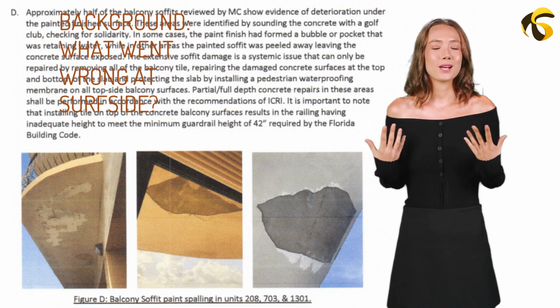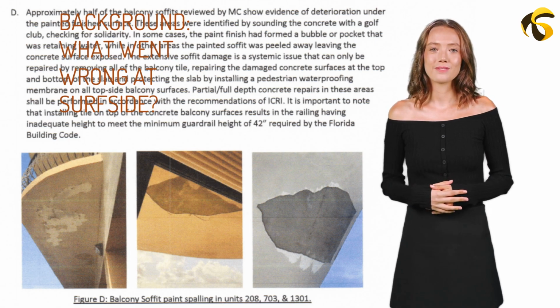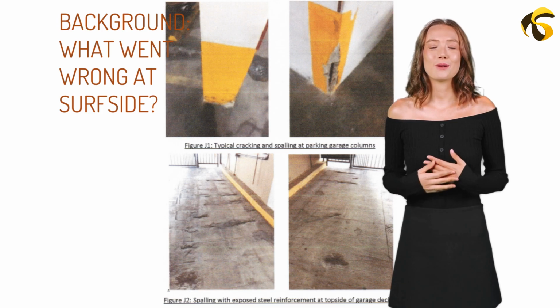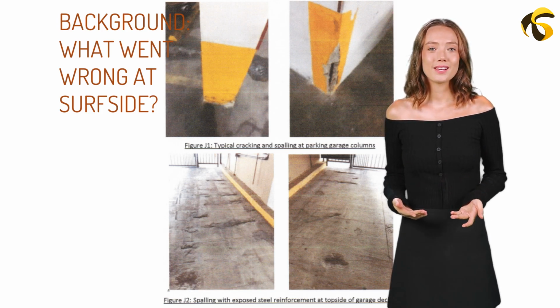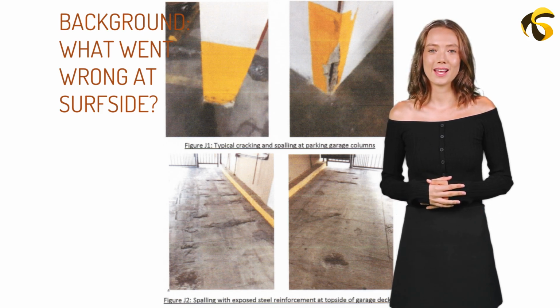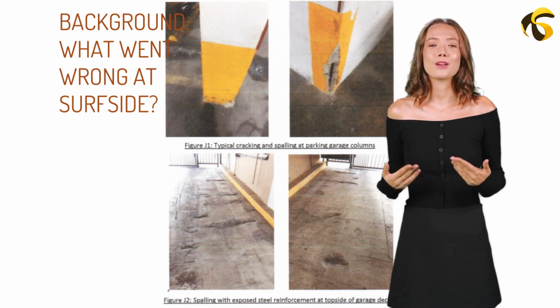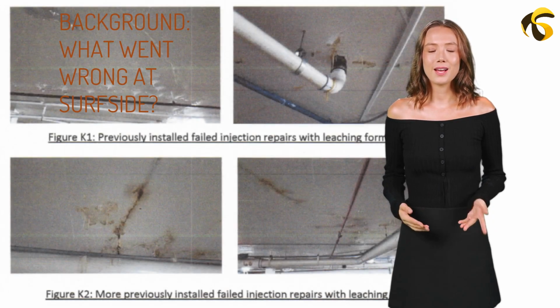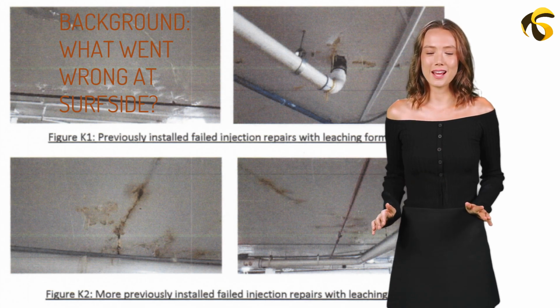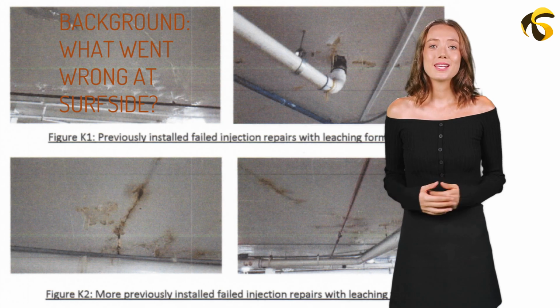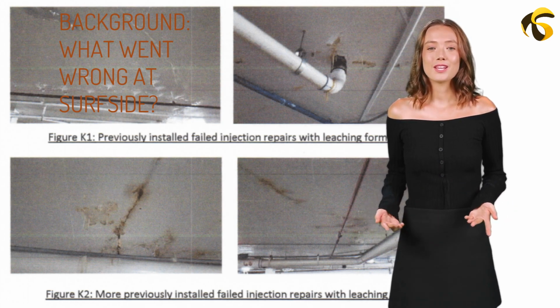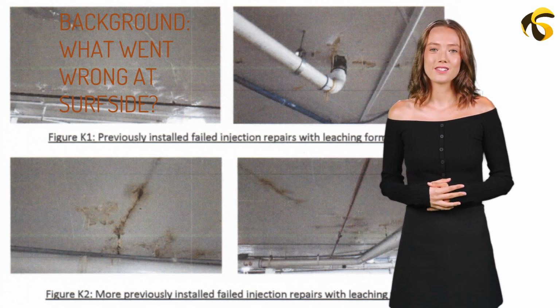concrete damage. The 2018 Morabito report urged prompt repairs. All the failed waterproofing needed to be removed and replaced to stop ongoing damage. The report starkly cautioned that if waterproofing was not fixed soon, the extent of the concrete deterioration would expand exponentially. In the same report, Morabito noted that many prior patchwork concrete repairs in the garage were already failing, likely because the root cause, water intrusion, had not been addressed. Unfortunately, these critical waterproofing repairs had not been carried out by the time of the collapse in 2021. The Condo Association had approved a $15 million package of remedial works, including pool deck and slab repairs, for the 40-year recertification, but work had barely begun when disaster struck.